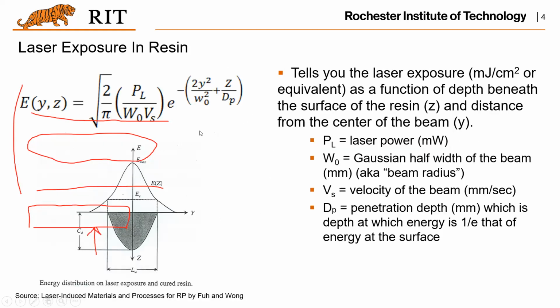All right, now we have this equation here, and basically PL is the laser power, and W0 is this Gaussian half width of the beam. As you can see here, that represents the beam radius, right? And this E(y,z) is the laser exposure. Basically, its unit is millijoule per centimeter squared or some other equivalent unit. But overall, it's the laser exposure.